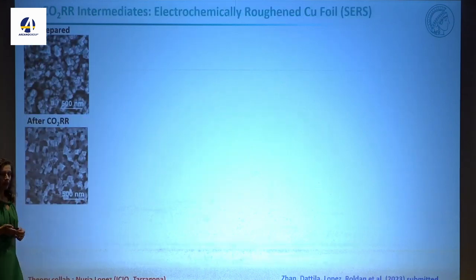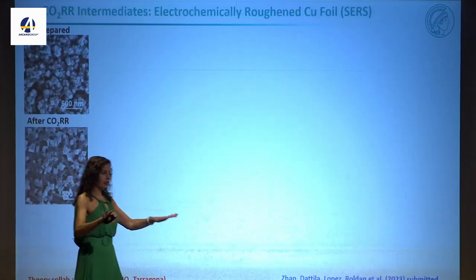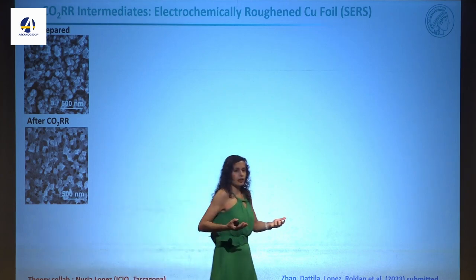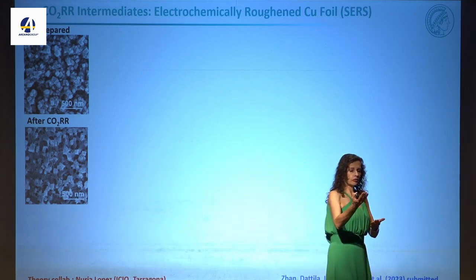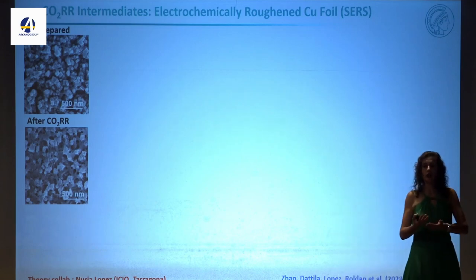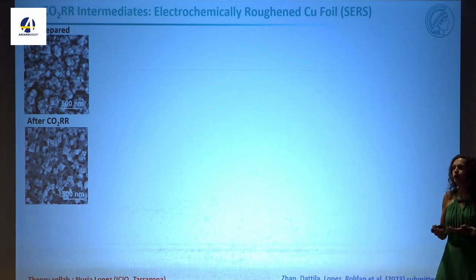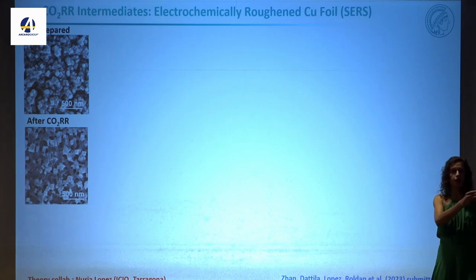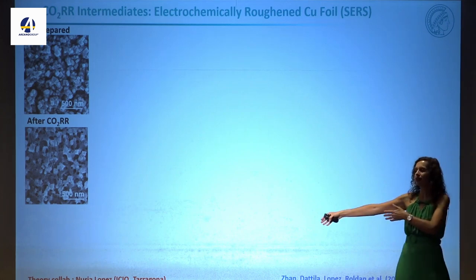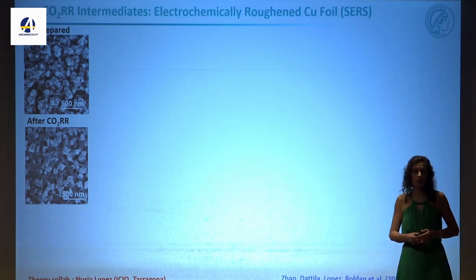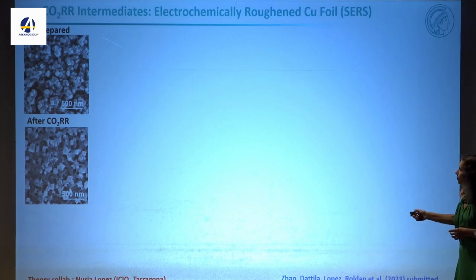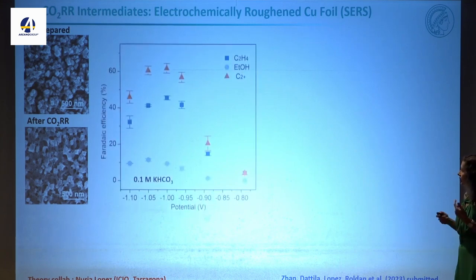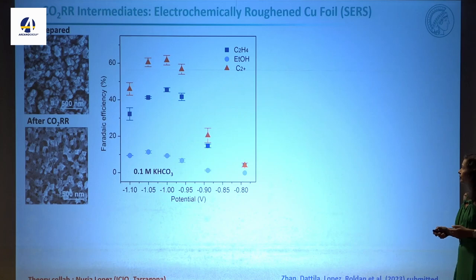So this looks nice, but if you're talking to the theorists, they show you many different reaction pathways, and they tell us, yeah, theoretically, sometimes going to ethylene versus ethanol energetically is very similar. Tell us what are possible intermediates that you can detect on the surface. And CO is at the very beginning, and we want to go to ethanol. So it would be nice to be able to see some other intermediates. So we spent a lot of time trying to develop very rough and very active surfaces, where we can have a very large surface-enhanced Raman signal. And then maybe we can see not only CO, but also some other intermediates. And we managed to do that very recently, so this is still unpublished.